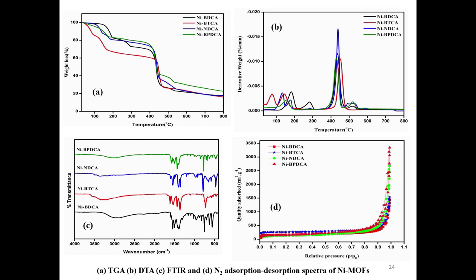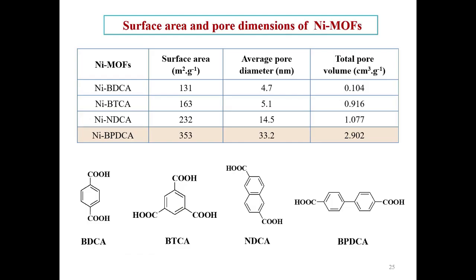When we have done the FTIR, it has been clearly observed that only the pure form of the nickel metal organic framework is synthesized with all the organic linkers, and no impurity is present. The adsorption-desorption spectra suggest the monodispersed form of the surface area and pore dimension of the nickel metal organic framework. Here nickel BPDCA shows a high surface area, that is 353 meter square gram inverse. Average pore diameter is 33.2, whereas total pore volume, centimeter cube gram inverse, is observed as 2.902.